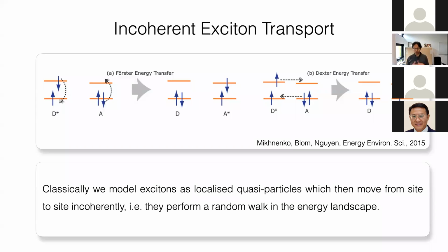It's basically two charge transfer integrals together. So it's mediated by the same nearest neighbor site-to-site interactions, just as charge transport is. And it is by its very nature, because of this, a very slow process, okay? And it requires close orbital overlap between the neighboring sites. So although it can happen for singlet or triplet excitons, when we're normally talking about singlet excitons, which are formed by light absorption, we tend to not deal too much with Dexter energy transfer. Of course, for triplet excitons, which have no dipole moment and are dark states, Dexter energy transfer is the dominant mechanism of transport.